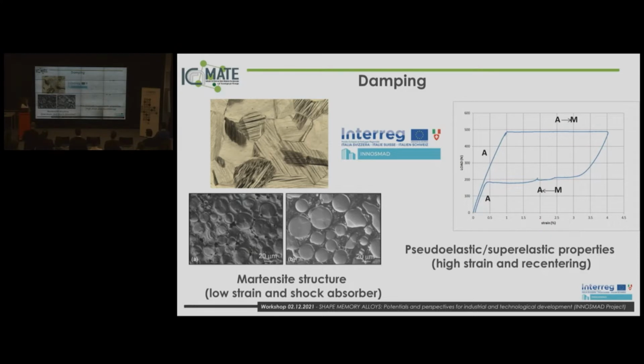The last application, but a very interesting application, which is the aim of our project, is the damping properties. The damping properties originate from all the effects of the shape memory alloys, the martensitic state, but also the pseudoelastic effect. Because in the martensitic state, we have this particular microstructure constituted by twins and so on, and this particular microstructure damps the low vibration of high frequency and low strain. But it is also a structure useful for shock absorbers, because the alloy can deform, absorb the shock, and then we heat the material and recover the initial shape. It is a shock absorber useful for more cycles of work, not for one cycle.